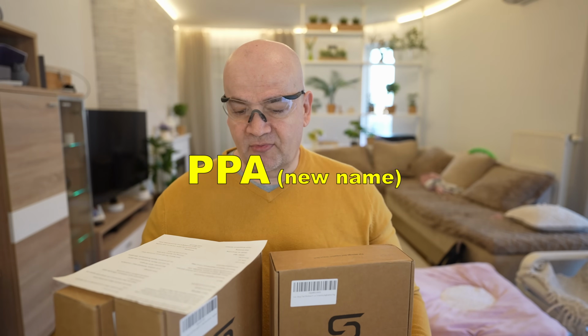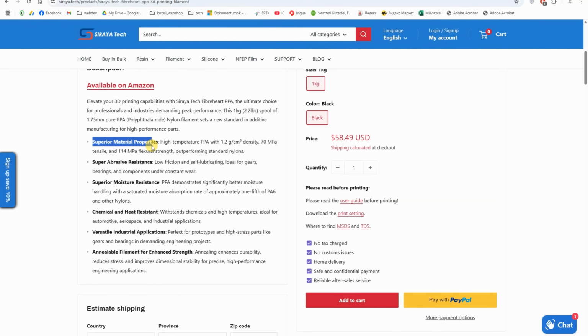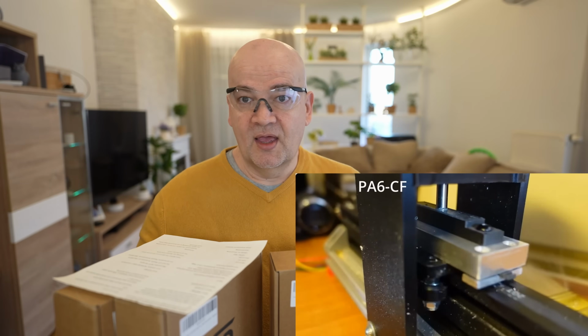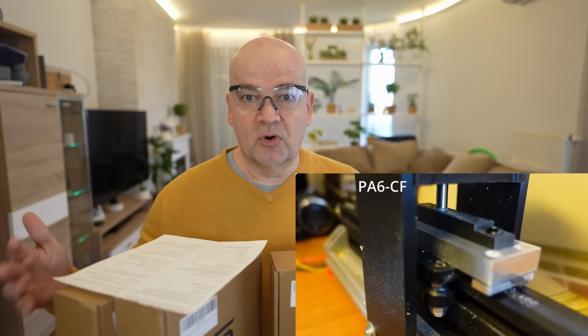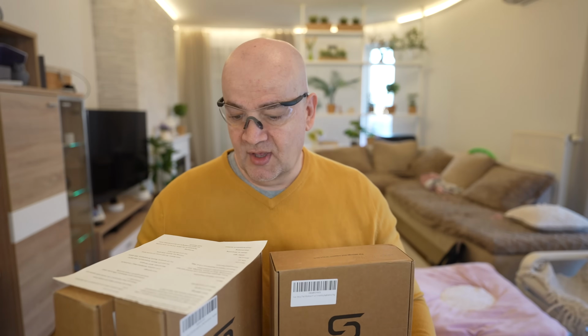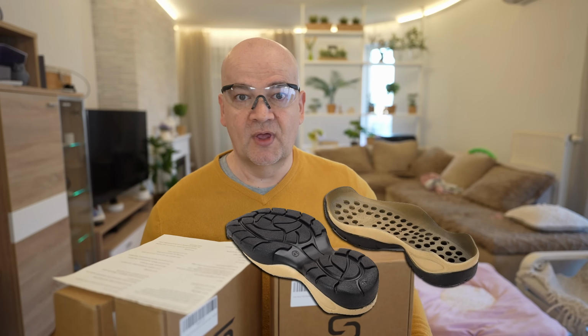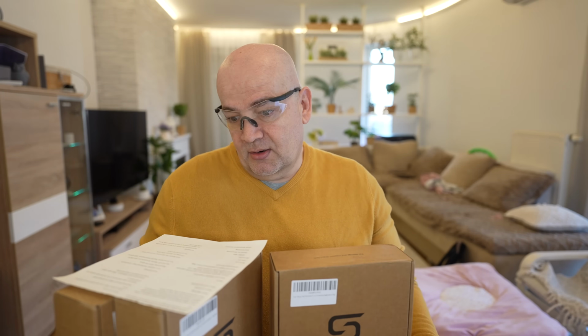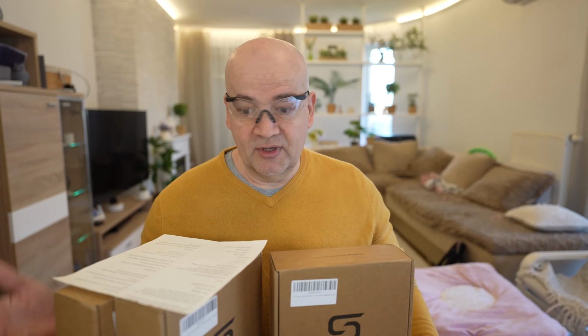PAHT, without carbon fiber, has superior material properties, super abrasion resistance, low friction and is self-lubricating, ideal for gears, bearings and components under constant wear. I already tested the wear of filaments earlier, and nylon and TPU are the two most wear-resistant filament types. Only with TPU we have more friction compared to nylon, so for example it is good for shoe bottoms. But if you need lower friction, then nylon is better. And here it looks like it is even superior in this case.